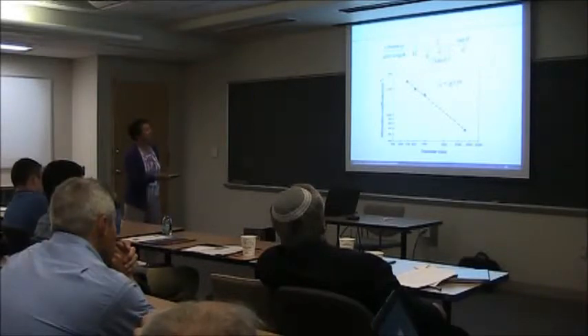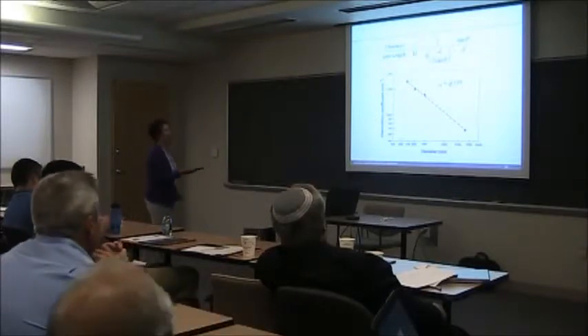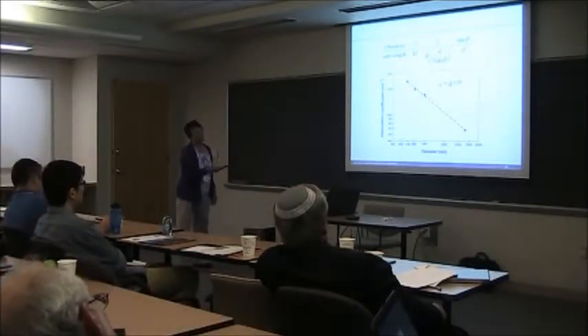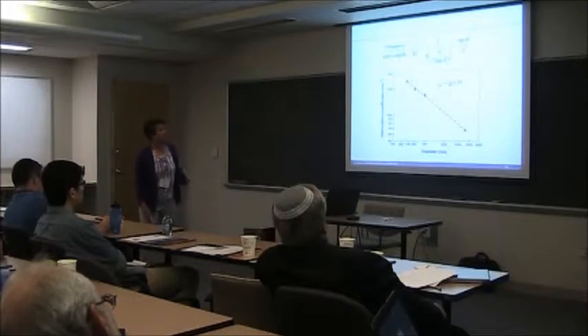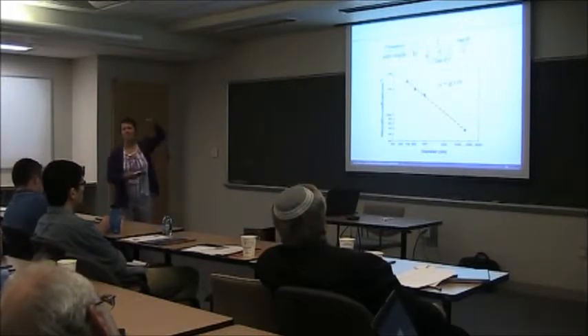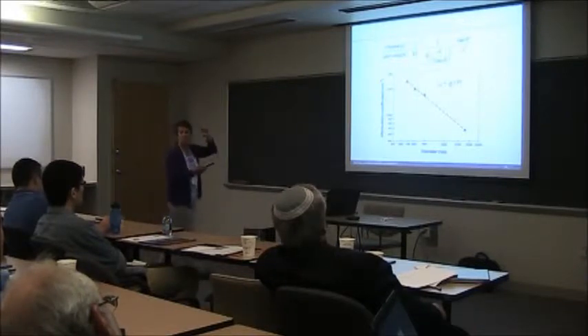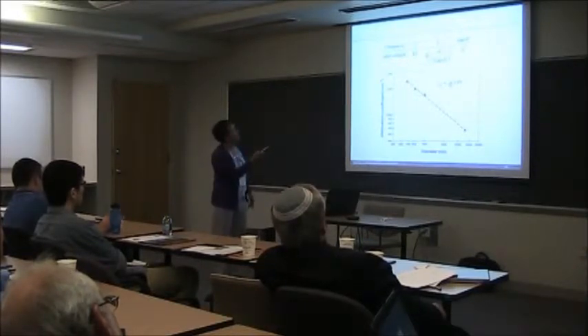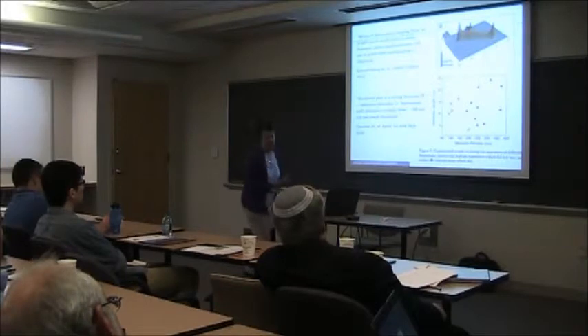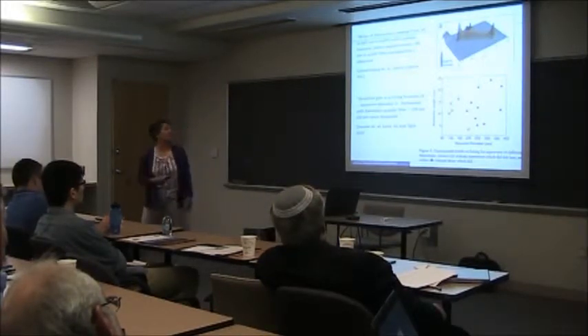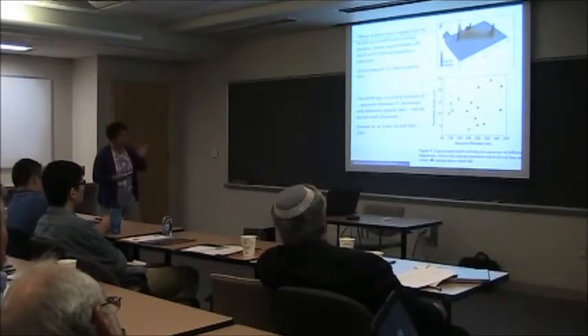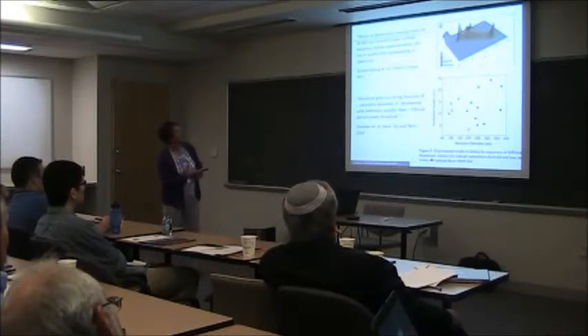Attenuation is a function of the diameter of the wire. The bigger the wire, the lower the attenuation coefficient. Okay? Slope around d to the -1. One very simple explanation is that the light being waveguided down the structure encounters the surface more as the diameter is smaller. If you model the number of bounces per unit length, it goes like 1/d. That's probably due to the fact that the surfaces aren't perfectly ideal. So we can get the number, but we see a dependence there through this technique.